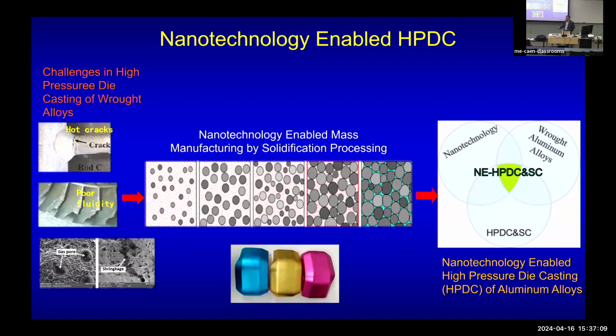And here, traditionally, we have a problem with high pressure die casting of high performance aluminum alloys, like wrought alloys, 6061, 2024, 7075. You cannot do high pressure die casting because hot cracks will kill them. And people tried, okay? It's not like people are not trying for a long time. It cracks like crazy. You couldn't solve the problem. And also poor fluidity, because they couldn't flow well, right? And also they have a lot of shrinkage and gas porosities. But with our nanotechnology, right, enabling mass manufacturing by solidification, we solve the problem, right? We eliminate this, and they enhance this, and they mostly distribute that, and also eliminate that.